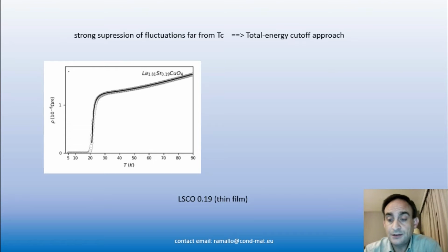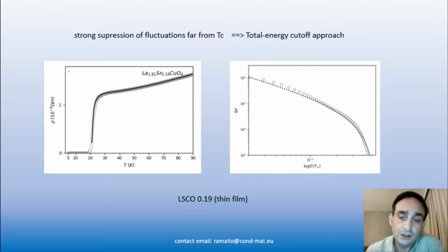So to explain this effect, we proposed from Santiago de Compostela that this is actually due to the limitations imposed by the uncertainty principle when you try to do a fluctuation that is smaller than the coherence length at T equal to 0. This can be expressed in terms of a total energy cutoff approach in the Gaussian Ginzburg-Landau approaches. And as you see, the agreement with experiments is actually good with the resulting expressions for that theoretical approach, even if you write it down in terms of the log-log slopes, if you extend that log-log graph to high temperatures.